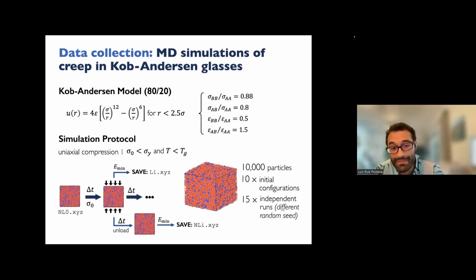The systems that we simulate have 10,000 particles. And so far we have simulated 10 different initial configurations. So when we prepare the glass, we generate a melt and then we cool it down. Right, so that process is very stochastic, especially at high temperature. So we repeat this process 10 times, which results in 10 different initial configurations of the glass.